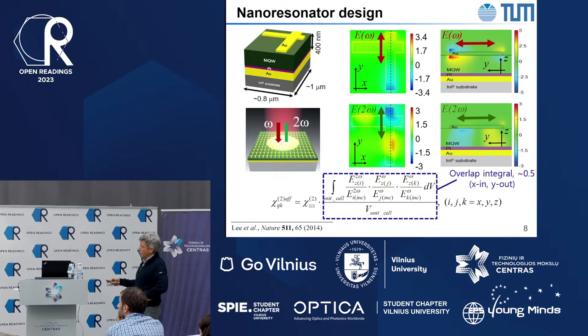And then the overlap integral, for example, here in this original demonstration was actually just half. So the effective nonlinearity was smaller than the original nonlinearity of Chi2, but it allows us to at least convert polarizations. We could now shine light at normal incidence.